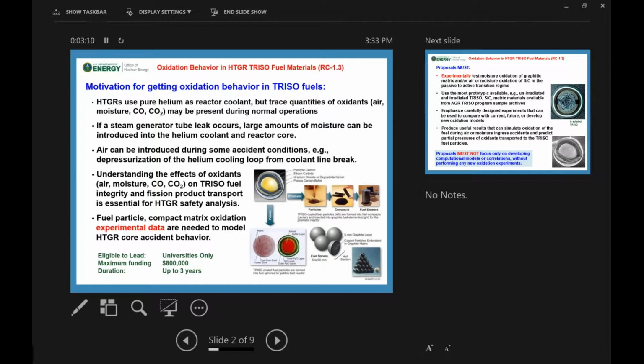So why are we trying to get oxidation behavior? Well, gas-cooled reactors use pure helium as the coolant, but sometimes we can get some oxidants, such as air, moisture, carbon monoxide, and carbon dioxide may be present during normal operations, and there are strict limits on that. If the reactor system uses a Rankine cycle with a steam generator, if there's a tube leak, we could have a lot of moisture entering into the helium coolant and into the reactor core, which basically will eat up the graphite.